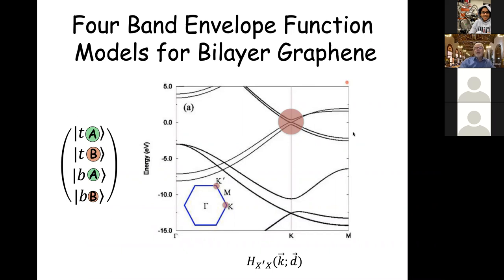So now I'm showing you a band structure, energy versus momentum, for bilayer graphene with a particular stacking between the two layers. This is for the equilibrium stacking, so-called Bernal bilayer stacking, in which one of the atoms of the honeycomb of one layer is in the middle of the hexagonal plaquettes of the other layer, and one atom is directly above the other layer. So that's the equilibrium structure of bilayer graphene.